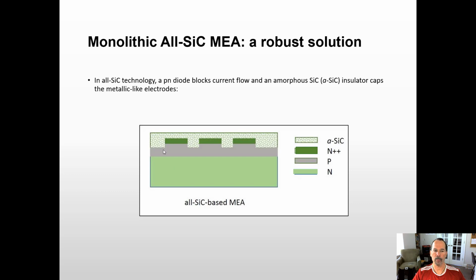We'd cap it with a heavily doped N+ layer, which has semi-metallic conduction, and then we cap the whole device using amorphous silicon carbide. Deep reactive ion etching is used to make these mesas. So I'm showing here in this example 3 parallel conductors going into and out of the board. So no plastics, no metals, only robust silicon carbide. So that's the goal.